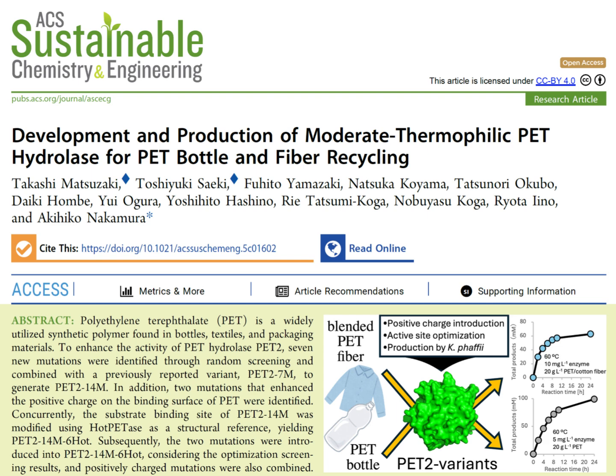Right. They show particular promise for those really challenging pure and blended PET fibers, thanks to that incredible specificity, just eating the PET, leaving the cotton alone. Exactly. And their superior performance at lower enzyme loadings compared to some established enzymes like LCC-ICCG is a massive potential win for making this economically viable on a large scale. Cheaper processing. Potentially, yes. And, maybe most critically, this work has really underscored the crucial insight about reaction temperature needing to be tuned to the properties of the entire polymer blend, especially considering things like the glass transition temperature of all components. It's subtle, but really powerful for practical application.